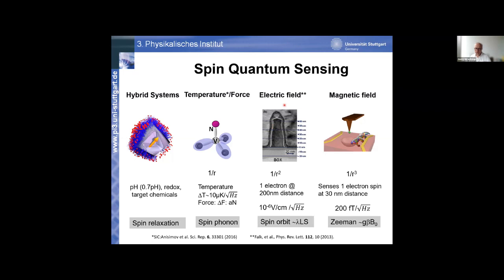One can also measure electric fields. So although diamond and also silicon carbide comprise light constituents, where you nominally would expect that spin-orbit coupling is very low, which indeed it is, it is sufficient actually to measure an electric field shift of the Zeeman level. So you can do Stark effect types of experiments. And this is once again due to the rather long relaxation and spin decoherence time. So you see these tiny shifts. People, and we have measured, so we have used it for electrometry. And just to give you an idea, we can measure the charge of a single electron spin at roughly, say, half a micron or 200 nanometer distance. So that's 10 to the minus 4 volts per centimeter per square root of hertz.